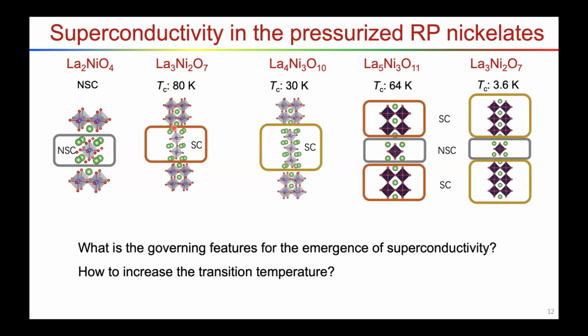For the bilayer phase, it's 80 Kelvin. For this trilayer phase, it's 30 Kelvin. This 1212 phase is more than 60 Kelvin. For this one, the 1313 phase is only 3.6 Kelvin.